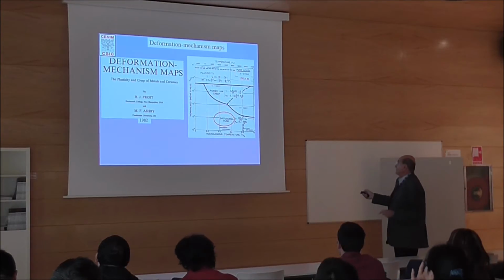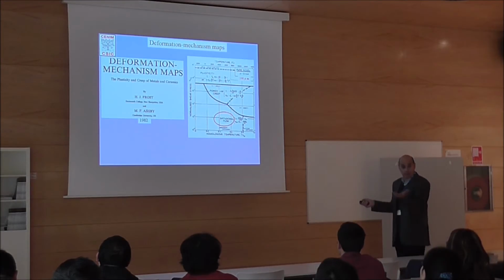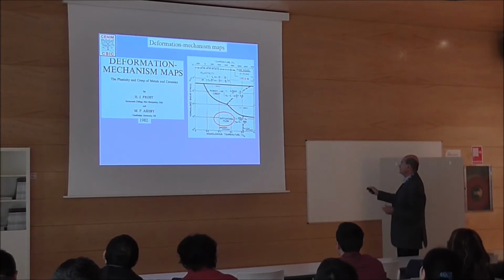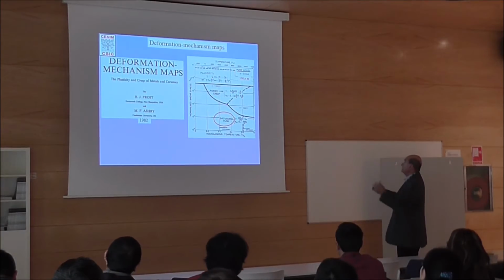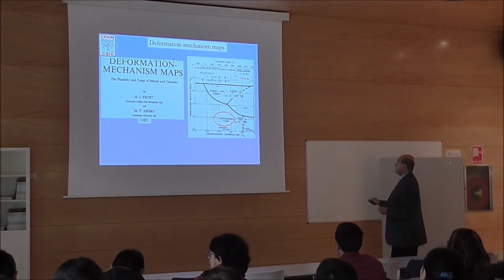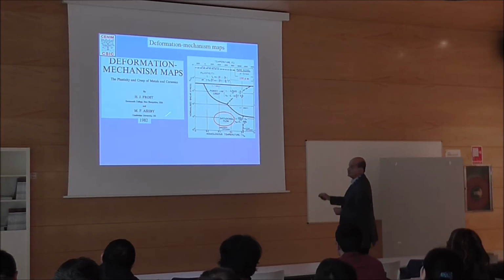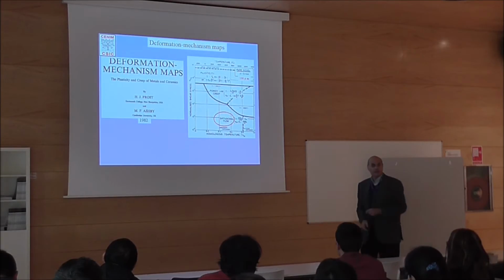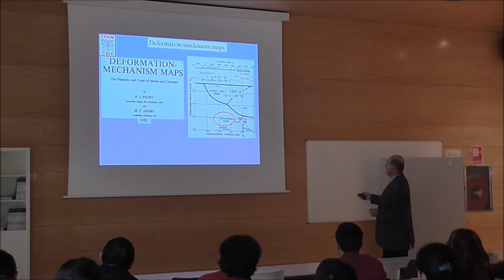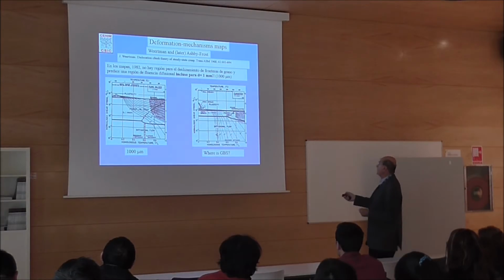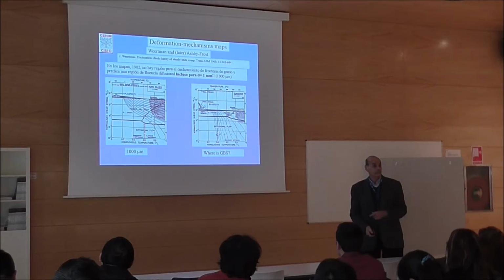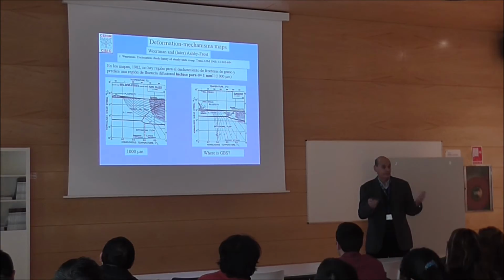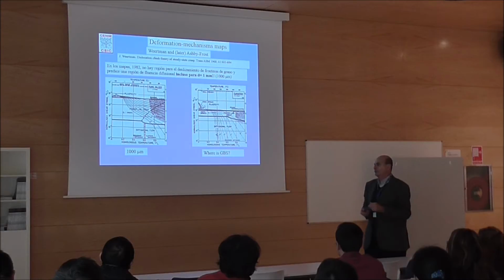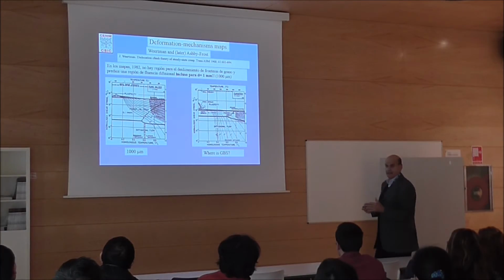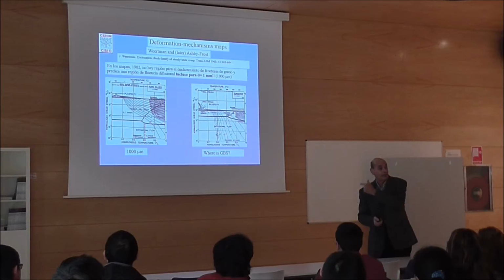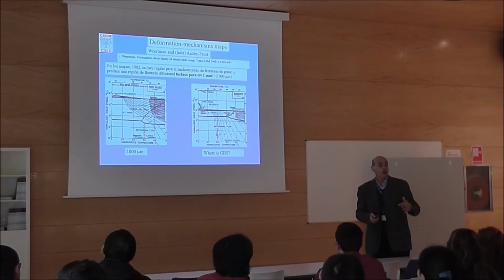And you can see here this type of maps. You have here power law creep, dislocation creep. This is also dislocation creep. This is another type that he invented, where everything is dislocation creep. And at low shear stresses, diffusional flow. But diffusional flow for 100 microns, and even diffusional flow for 1 millimeter, which is nonsense. You cannot have diffusional flow at such big grain size, because the Nabarro-Herring equations will predict extremely low strain rates.